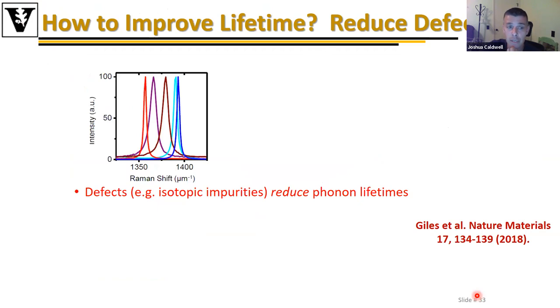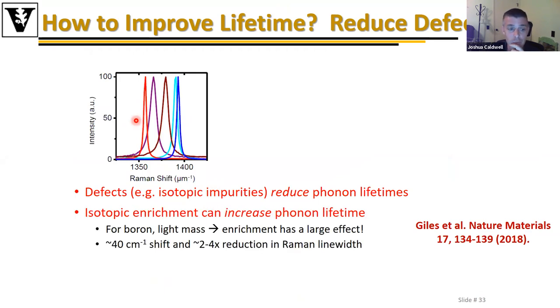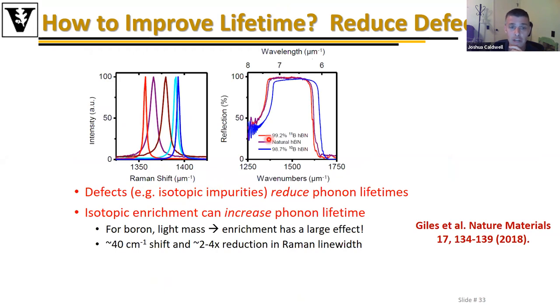And we're going to be using lower loss hexagonal boron nitride, which is provided by Jim Edgar, which is isotopically enriched. As you can see here, boron in hexagonal boron nitride is naturally about 80% boron 11 and 20% boron 10 isotopes. And so if I make this purely boron 10, I can shift this LO phonon to very high frequencies and significantly narrow the line width by reducing scattering. Or purely boron 11, I can do the opposite and shift this to lower frequencies. And you can see that corresponding shift in the Reststrahlen bands shown here.